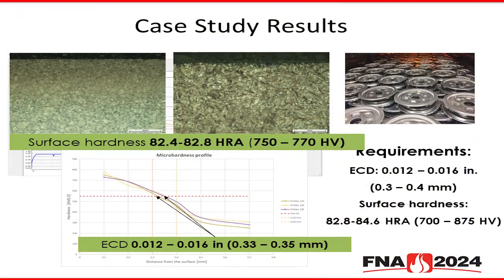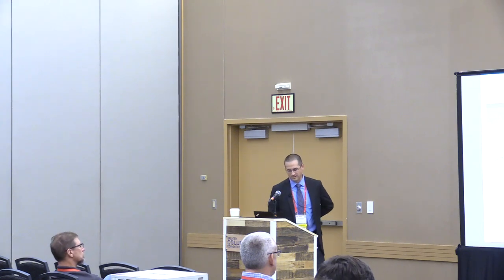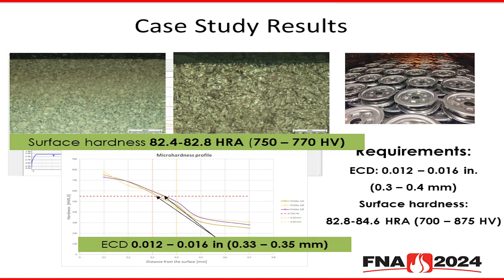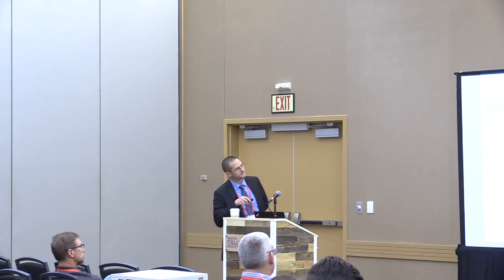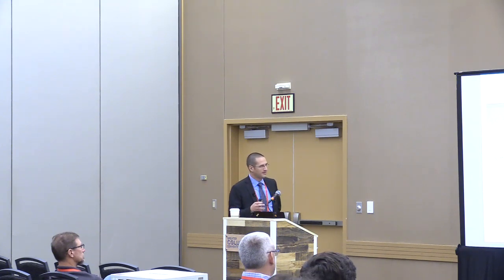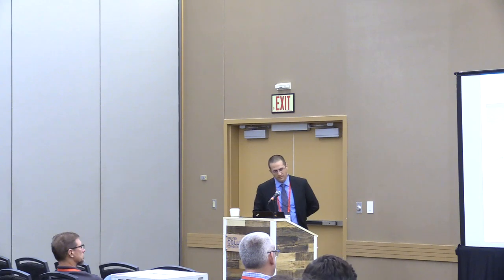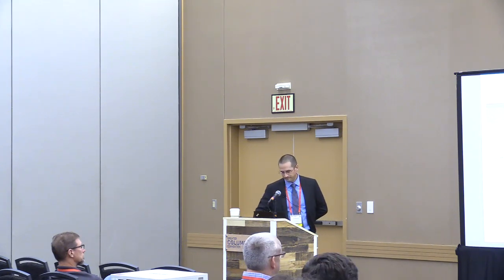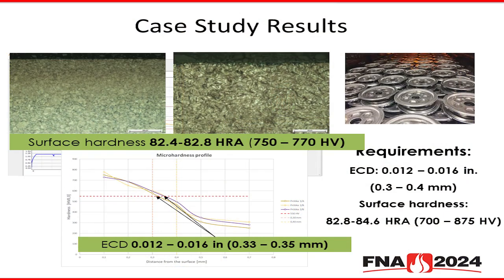With that, here is an SEM microstructure of the end result. The one on the left is at 500 times magnification. The one on the right is at 1,000 times magnification. As you'll see, the results are mostly martensite with a small amount of retained austenite, but for the most part, we've achieved our goal. We've reached a surface hardness of roughly 82.5 to 82.8 Rockwell A, or between 750 and 770 Vickers. And we've achieved a case depth of around 0.33 to 0.35 millimeters, again our target case depth at the beginning.